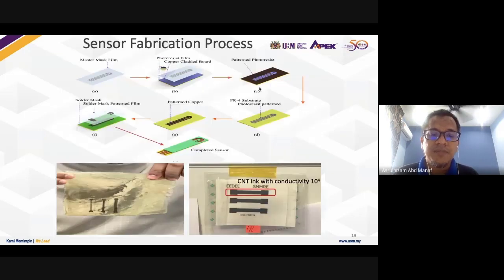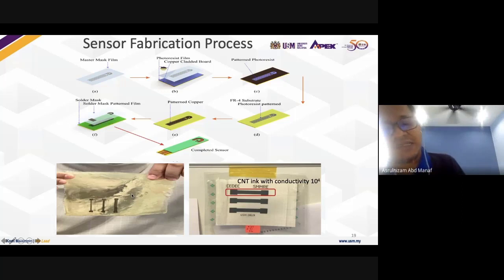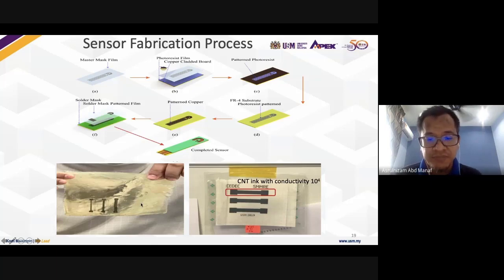We also did fabrication, and that technique is of course towards a smart bandage. We bought bandages from pharmacies and printed CNT ink on them. That was our first test, on the conductivity, and we also tested on gelatin to see the adhesion between the ink and the substrate.